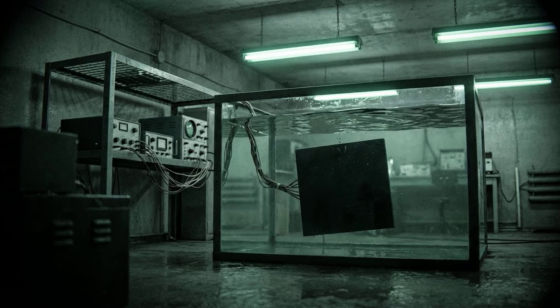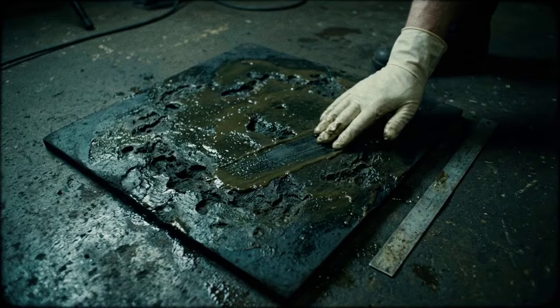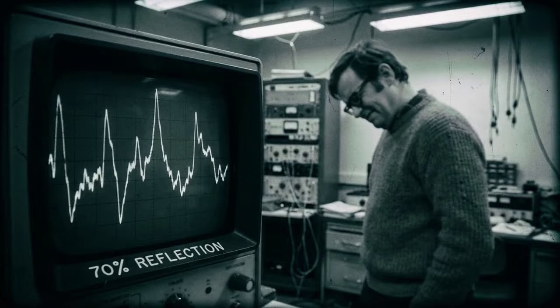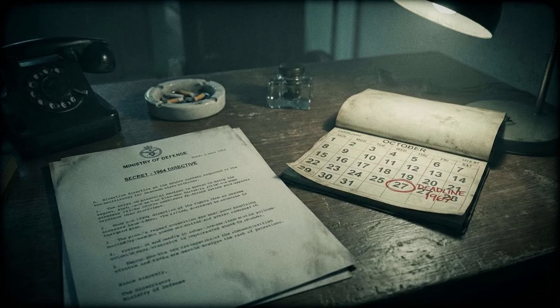steel test plate. The tile goes into a seawater immersion tank at 18 degrees Celsius. After 6 weeks, the rubber surface has begun to dissolve. Polymer chains are breaking down in the salt water, and the material has lost structural integrity. The engineers pull the tile out and test its acoustic absorption. It fails to match the original German performance profile. Incoming sonar pulses pass through the degraded rubber and reflect off the steel backing at 70% strength, instead of the target 15%. Moscow issues a directive in early 1964.